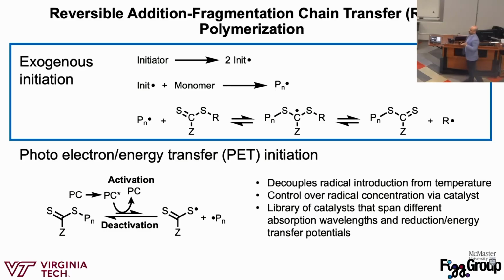And so the conventional advantages are that you start all of your chains from your RAFT agent, and you can control the photocatalyst concentration and radical concentration. These are what we're really interested in in my group. Conventionally you run a polymerization according to how you're introducing radicals and the Kp of the monomer. But what's really nice about this photocatalytic technique is that you can actually decouple radical introduction from temperature.